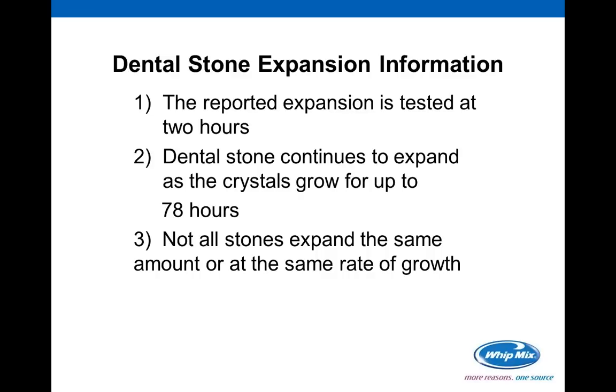You also need to know, however, that dental stone continues to expand after that 2-hour mark as the crystals grow, and it can expand for up to 78 hours. Now, what's important about that is that for years and years, dental technicians and even dentists have been taught or assumed that the reported figure was the maximum expansion of that material, and that is not correct. Each material has its own little expansion that it continues to do as the crystals, which is what gypsum is, continue to grow.